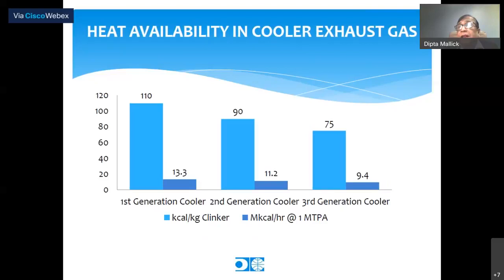And another area where you have a lot of hot exhaust gas is the cooler. In the cooler, the first generation cooler gives you 110 kilocalorie per kg, whereas the best coolers nowadays give 75 kilocalorie per kg. So that means from the preheater and from the cooler, you have a sufficient amount of energy. Now, can we utilize it fully?